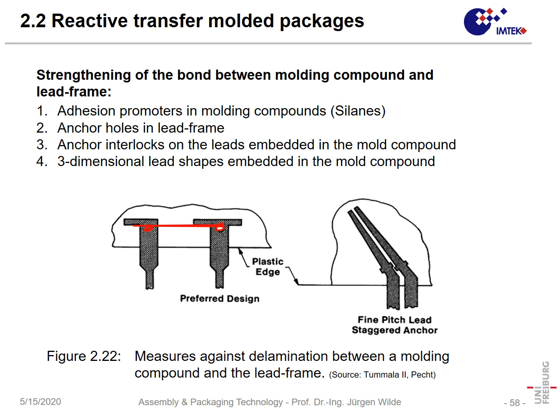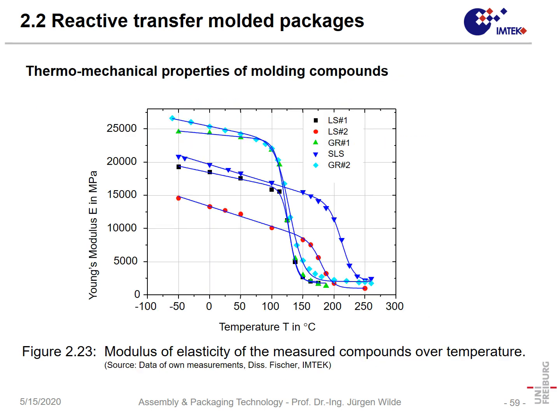So the lead frame is either etched, if it's a very thin material, just by photolithography and etching, or by some mechanical stamping process. And in both cases, it is quite easy to bring the lead frame into every two-dimensional shape which we desire. Now, let's have a closer look at the properties of such lead frames.